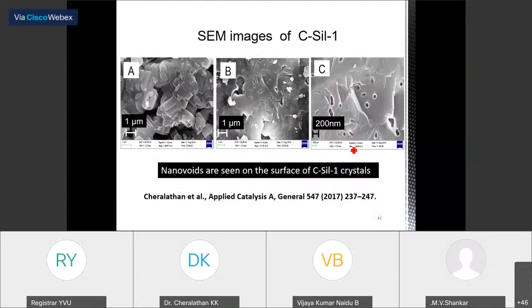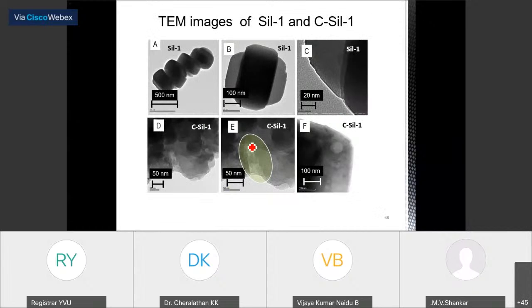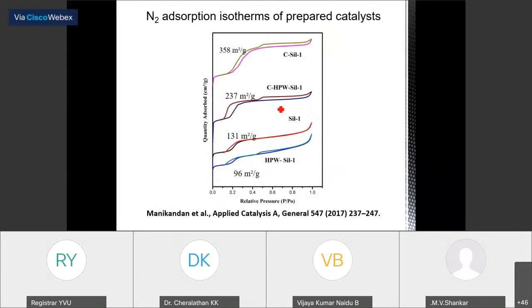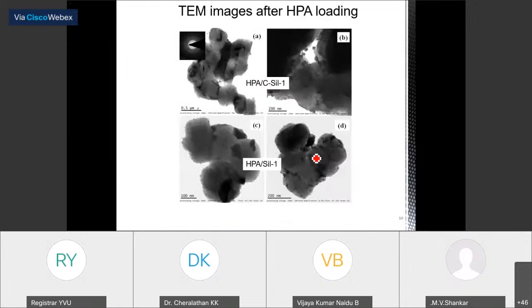And some characterizations I will show. This shows how these additional pores are present on the surface of the zeolite crystal. And then the TEM image shows a channel which is passing from the surface to the interior. In the conventional zeolite, it is not there. In the case of the zeolite prepared by us, you can see this channel. Then the adsorption isotherm, of course, indicates the presence of micropores as well as mesopores. Then this is after loading HPA, heteropolyacid. So the heteropolyacid is entering into all the channels and is held by the support.